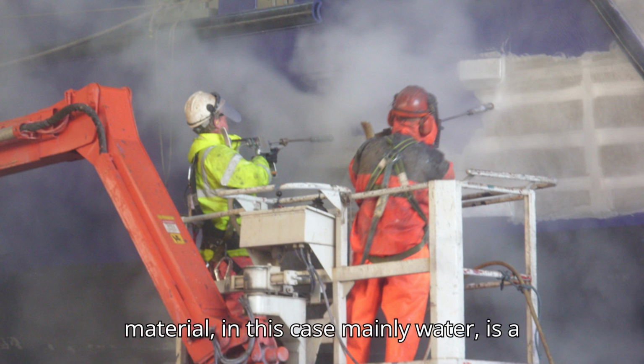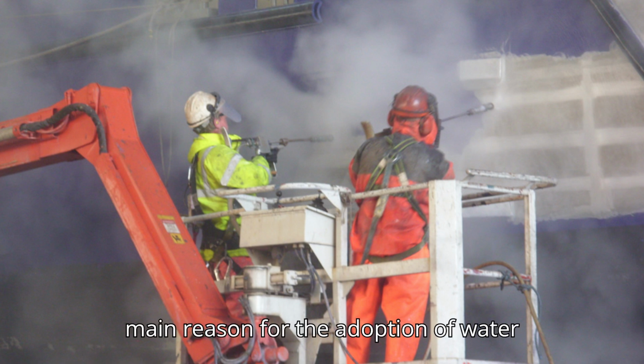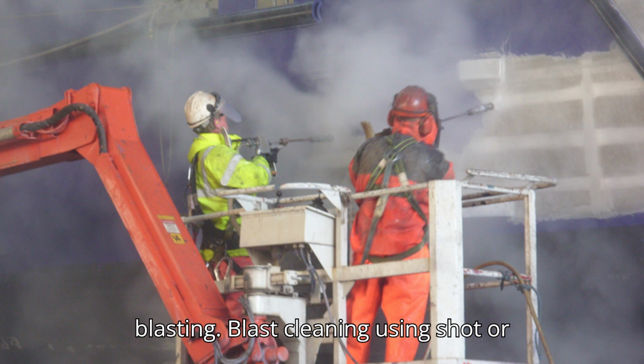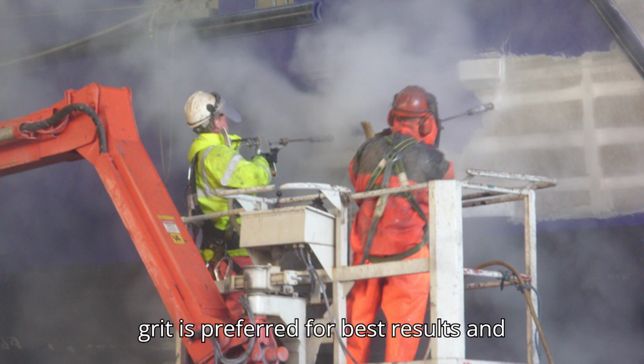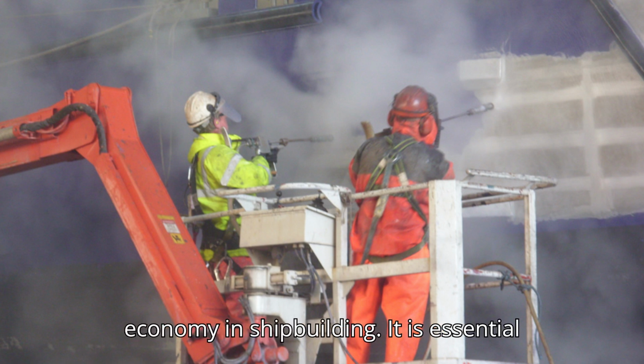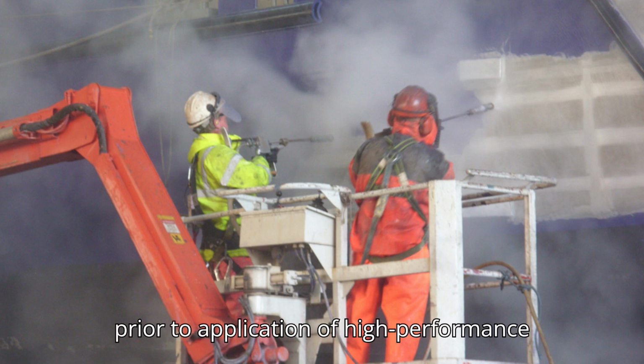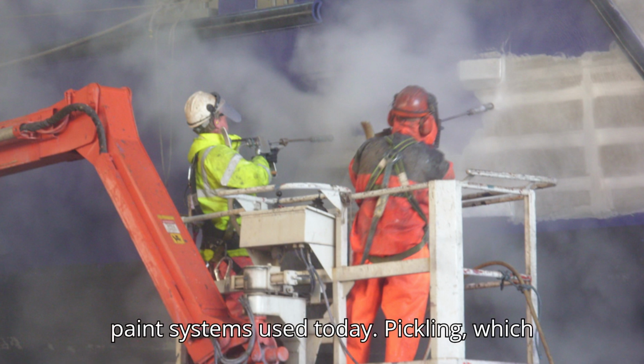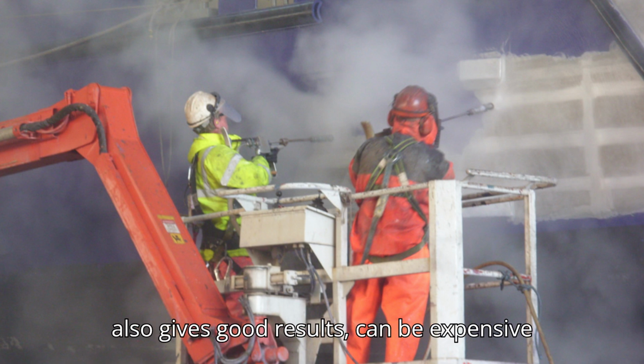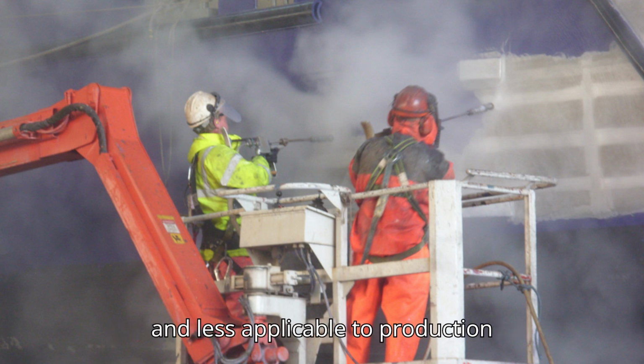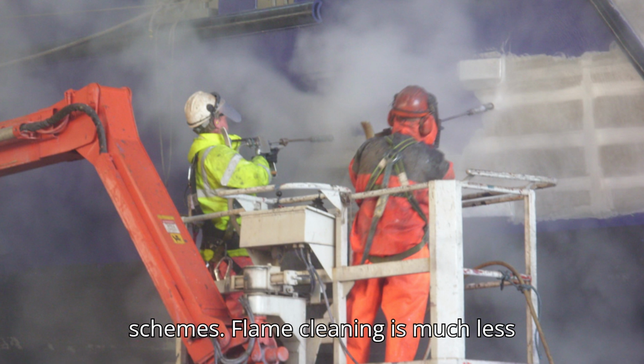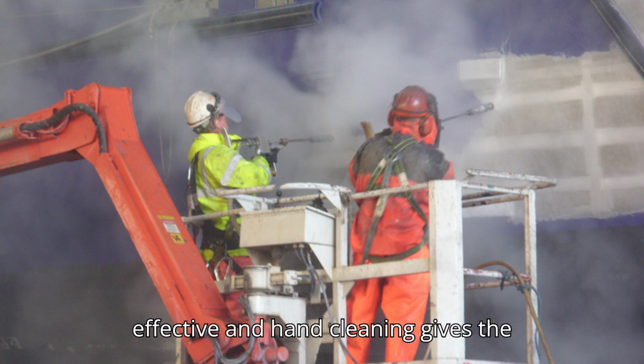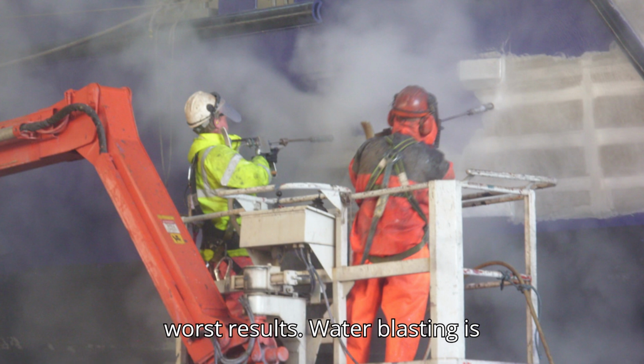Disposal of the waste material, in this case mainly water, is a main reason for the adoption of water blasting. Blast cleaning using shot or grit is preferred for best results and economy in shipbuilding. It is essential prior to application of high-performance paint systems used today. Pickling, which also gives good results, can be expensive and less applicable to production schemes. Flame cleaning is much less effective, and hand cleaning gives the worst results. Water blasting is mainly a ship repair process.